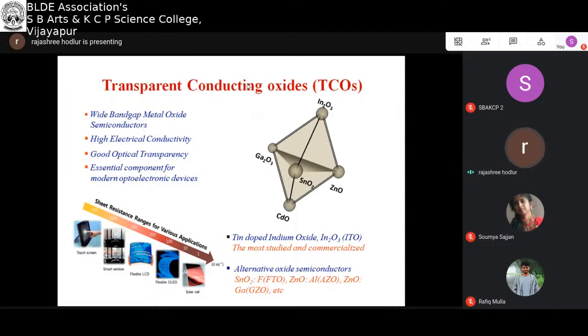to the nano regime, but since I discussed the liquid phase growth, liquid phase growth can not only be used to obtain powders or clusters, it can also be used to obtain thin films. Okay, so transparent conducting oxides can be obtained using these liquid phase growth techniques. So these transparent conducting oxides mainly have wide band gaps in the range 3 to 3.5 electron volt. Then they have very high electrical conductivity, good optical transparency, and they are the main components of modern optoelectronic devices.